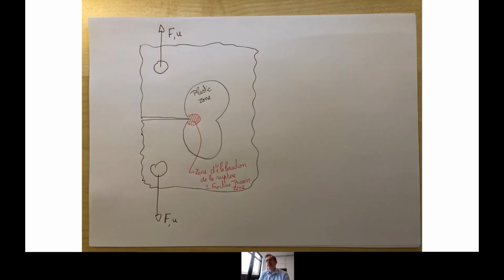I just want to introduce the concept of the fracture process zone. At the tip of the crack, when you load the specimen, of course you develop a diffuse plastic zone, but you also concentrate the plastic strain and the damage in a zone which will ultimately be the zone in which the material will fail. This is called the fracture process zone, in French the zone d'élaboration de la rupture. There is a well-defined definition for the fracture process zone given by Broberg.